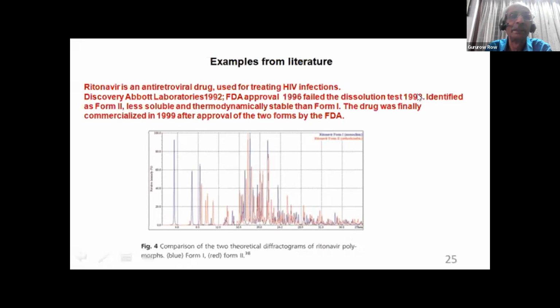What really happened was that Form 2 is less soluble and more thermodynamically stable than Form 1, and therefore Form 1 got converted to Form 2. XRD clearly illustrates this in terms of these red lines, which refer to Form 2, and the blue lines, which refer to Form 1. And you see the 2 are very different from each other.